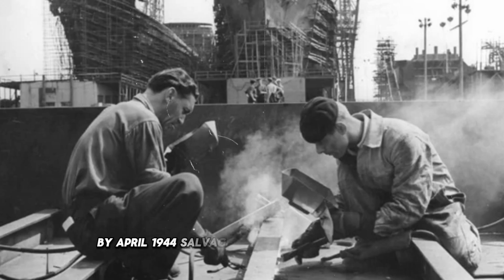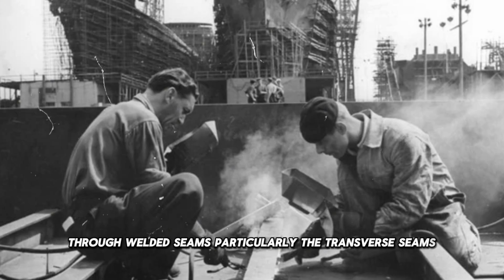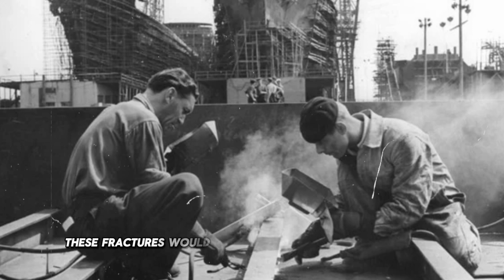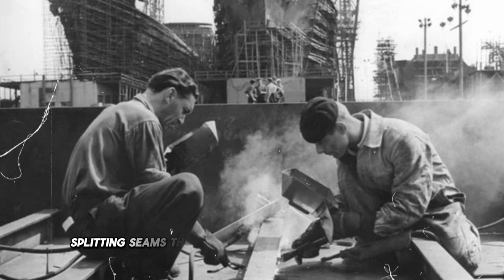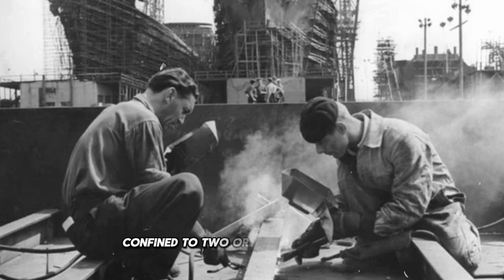By April 1944, salvage teams in the Mediterranean were seeing consistent patterns in how LSTs broke apart after mine strikes. The initial blast would crater the bottom plating, creating a hole between 6 and 12 feet in diameter. That was survivable if the ship's compartmentalization held. But the blast also propagated fractures through welded seams, particularly the transverse seams that ran across the hull. These fractures would race outward from the blast point, splitting seams that should have contained the flooding. Within seconds, what should have been damage confined to 2 or 3 compartments became catastrophic flooding of the entire forward section.